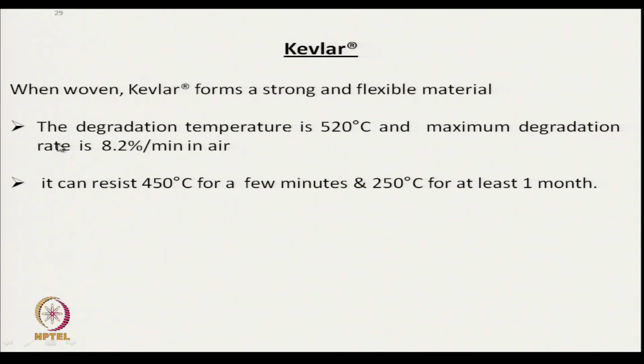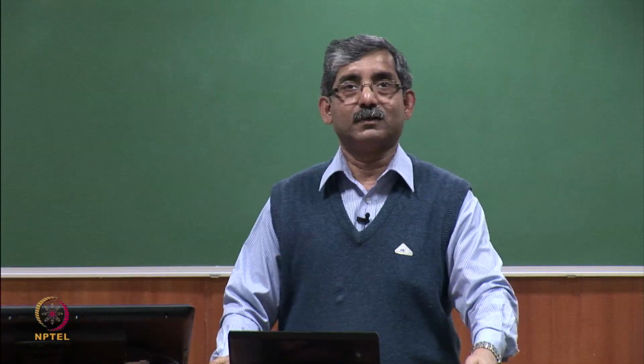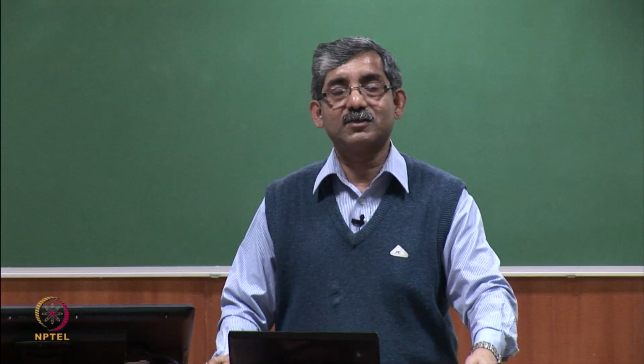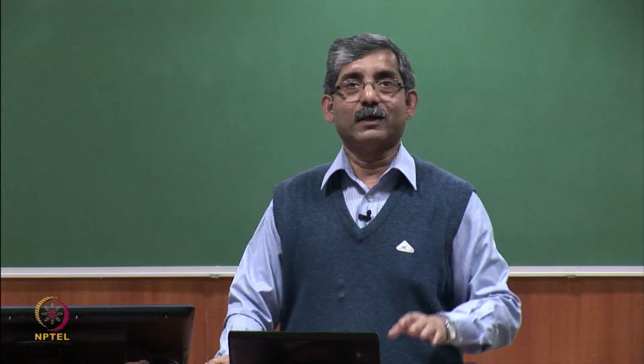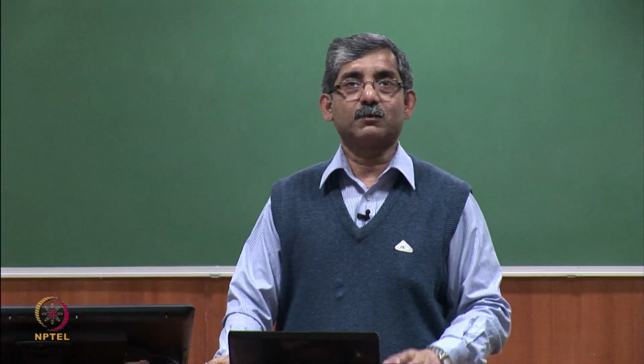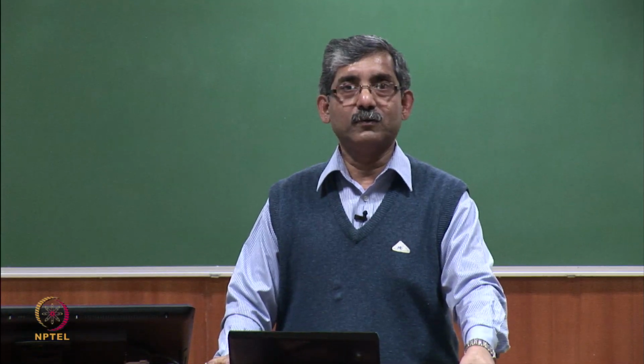As far as degradation is concerned, the degradation temperature is 520 degree Celsius and the maximum degradation rate is 8.2% per minute in air. So, it can resist 450 degree Celsius for a few minutes, and at 250 degree Celsius it can retain its strength for at least 1 month. So, at high temperature conditions this fiber is useful.